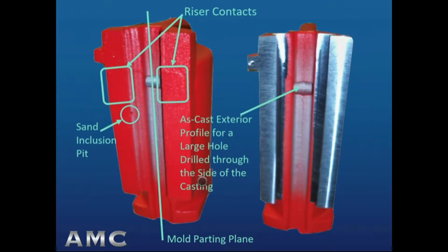Here are some as-cast features that are important to the machining of this casting. First, the mold parting line is along the major axis of the casting along its length. Second, you can see riser contacts on the bottom of the features that will become the dovetails. It is important for the foundry to grind those riser contacts down near the adjacent mold surface, but not below it.